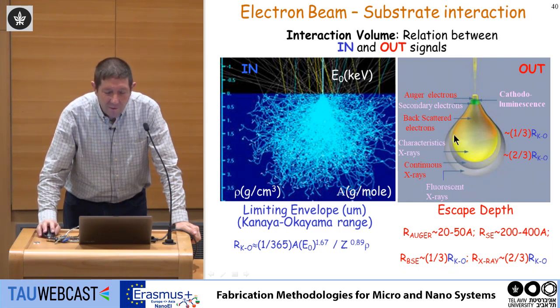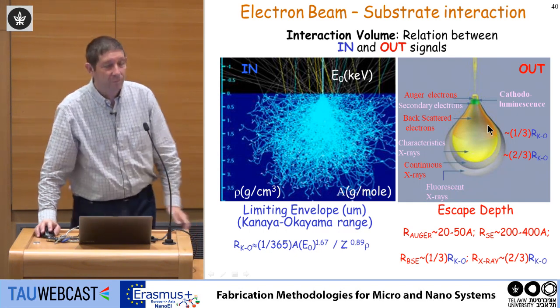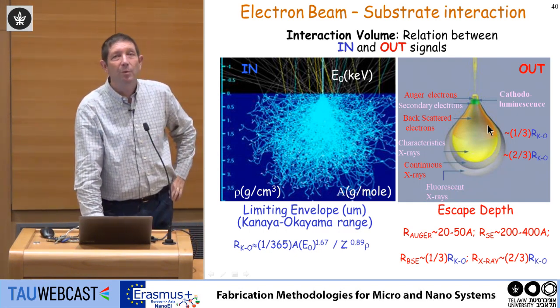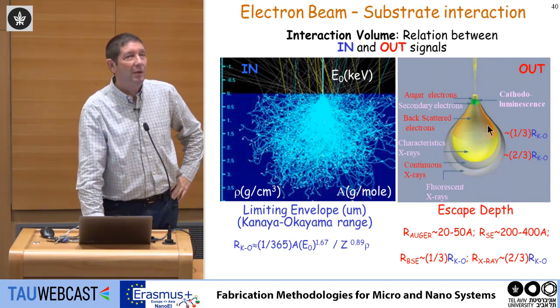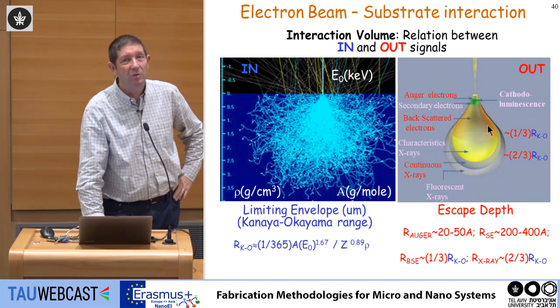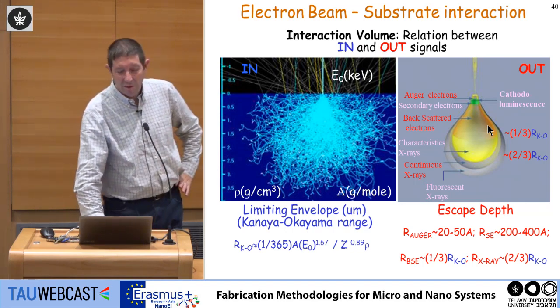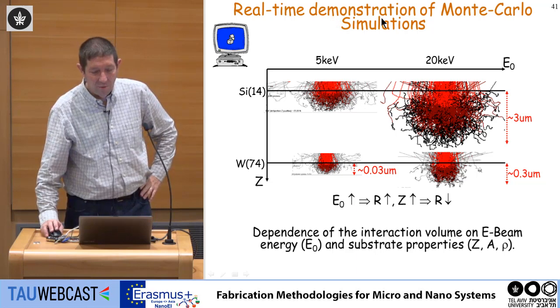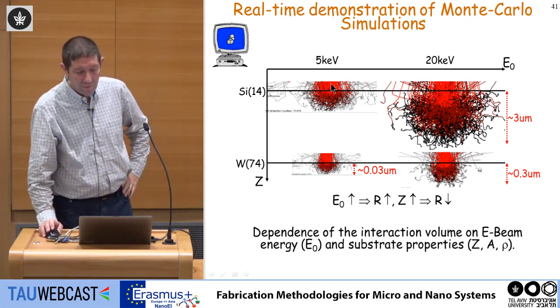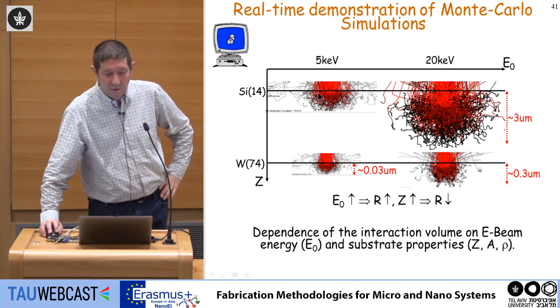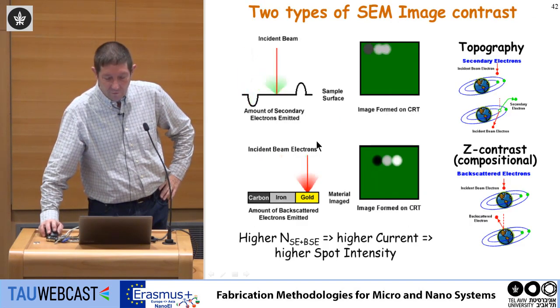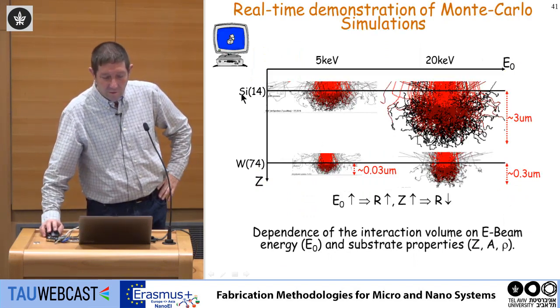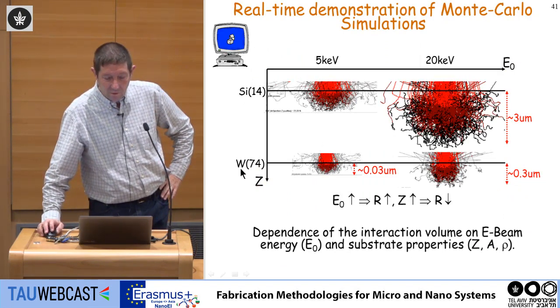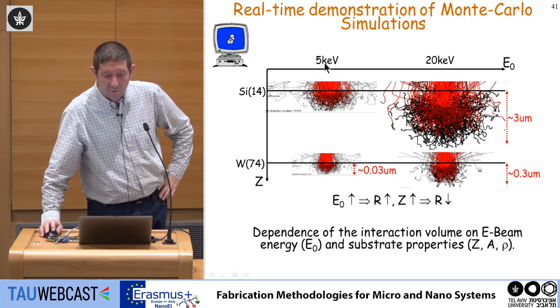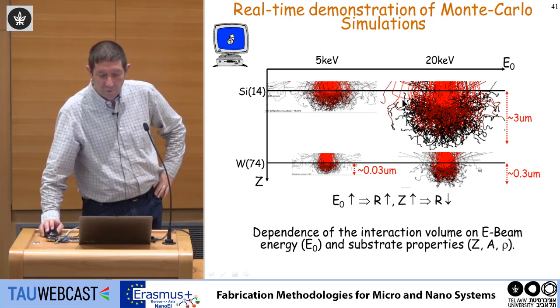But a rule of thumb is that you are collecting signal from a relatively large volume. So one way to reduce the volume is to reduce the energy. But if you reduce the energy, you increase the wavelength. So there are some limits. This is a nice real-time demonstration of a Monte Carlo simulation. This is a 5 kilo electron volt electrons into silicon. This is tungsten. So if you're shooting 5 kilo electron volt electrons into silicon, this is the volume of interaction.